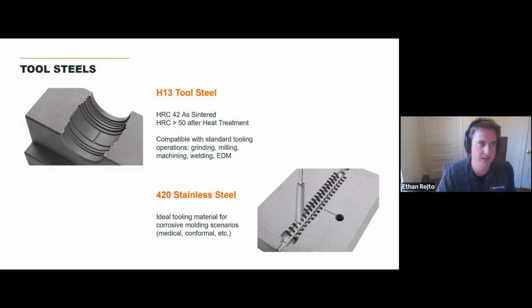In terms of materials, very commonly asked, we print some industry standard tool steels. H13, which is commonly known as really the workhorse of injection mold steels, comes out of the furnace at about 42 Rockwell as sintered. And if you wanted to afterwards, you could go ahead and heat treat that up to over 50. A newer material for us is 420 stainless steel. This was a result of feedback from mostly our medical device customers who really wanted a corrosion resistant tooling material. It's ideal for those applications, and another great, very common tool steel.